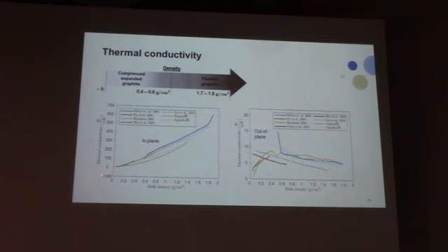Okay, so the thermal conductivity in the in-plane direction can be even 2 orders of magnitude higher than the thermal conductivity in the through-plane direction. This shows the high anisotropy of this material. So the data from literature are in agreement.